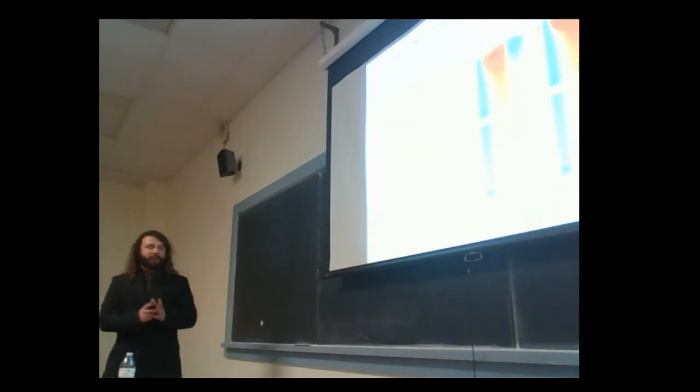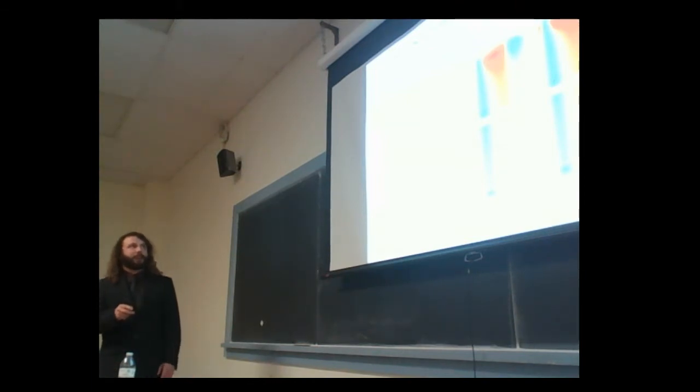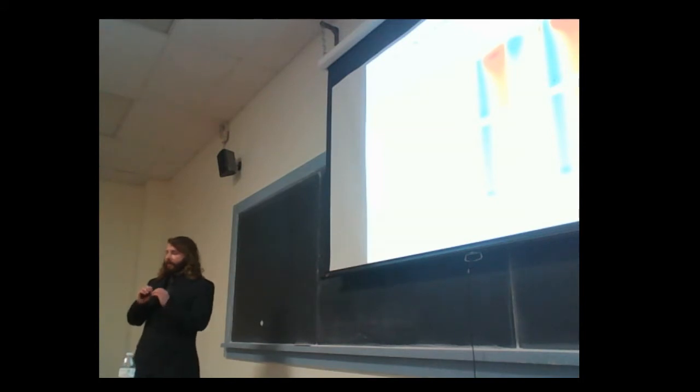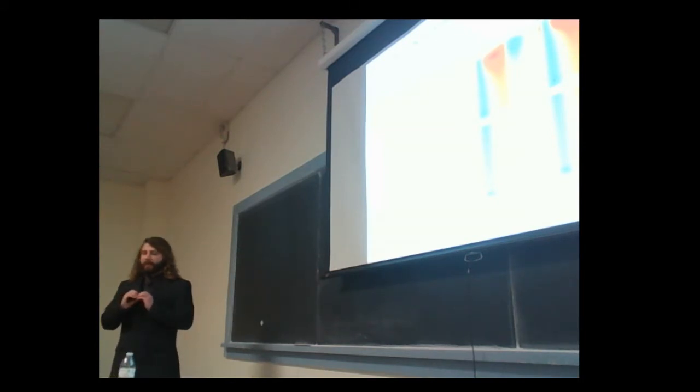And then this is multiplied by a decay associated spectra. So a decay associated spectra, as the name implies, is an optical spectra associated with a particular exponential decay. So what you want to think about this as is the amplitude of the difference in optical density at each wavelength for the exponential decay. So this is just like the amplitude of the exponential decay for each wavelength.